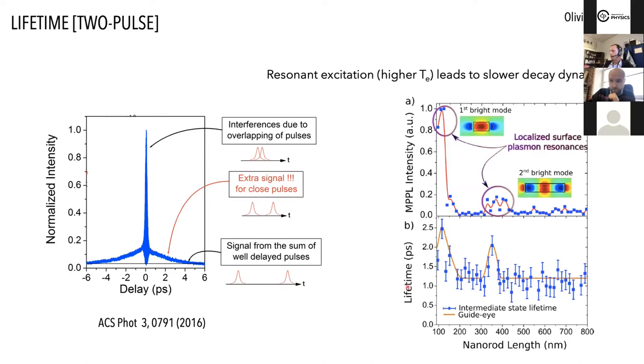And what we found back in the day is that this lifetime depends on the resonance. If you do this on a nanowire or nanorod, you can have different resonances, and this is a function of length. So you can see a first resonance in the signal here, a first resonance there, and the second there. And what we can see is that this lifetime, that is basically the exponential decay of that curve here, depends on the presence of a resonance excitation.